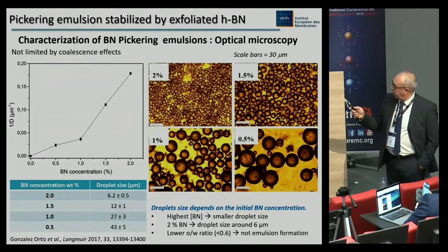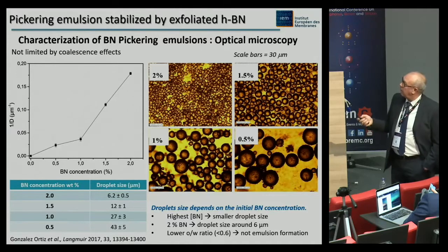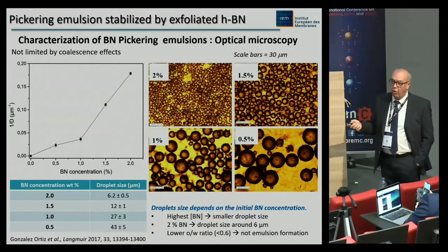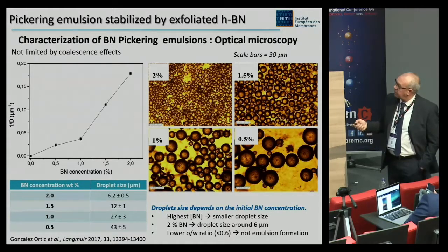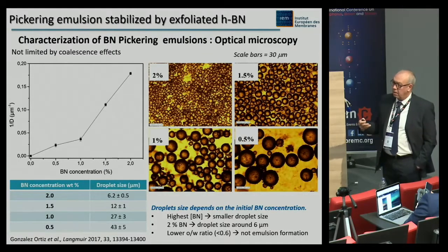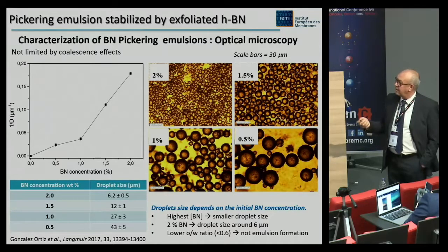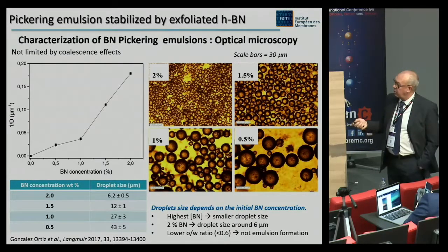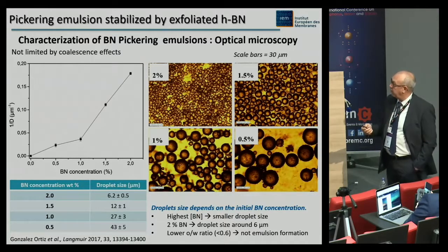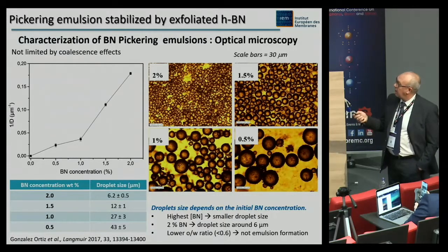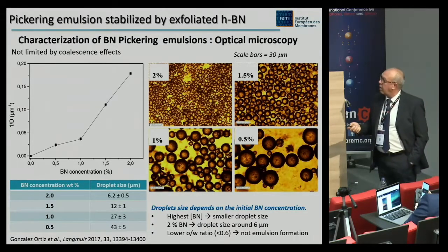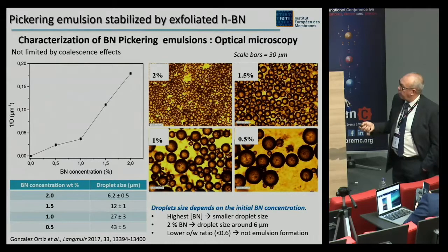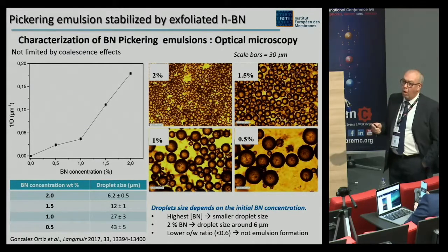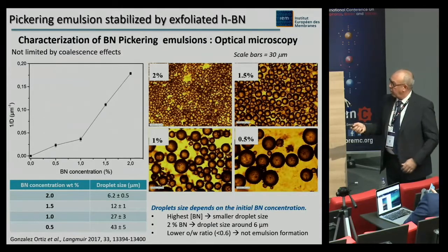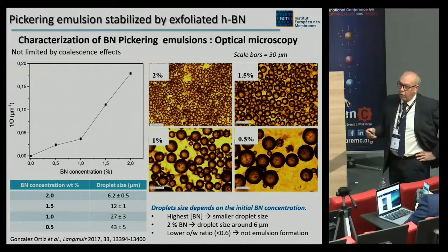Now the photographs of the emulsion. You have this system with different ratios of BN, and you can see that the size of the droplets depends on the concentration of BN inside the emulsion. The highest concentration of BN led to the smaller droplet size, and for 2% of BN, the droplet size is around 6 micrometers. And if you use a low oil-to-water ratio, for example lower than 0.6, you have no emulsion formation.